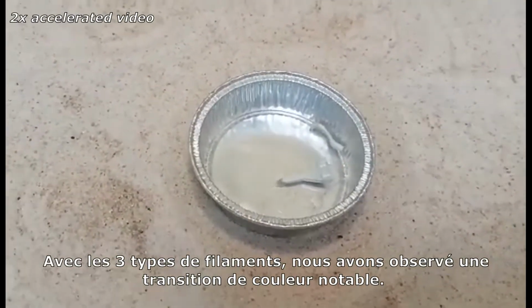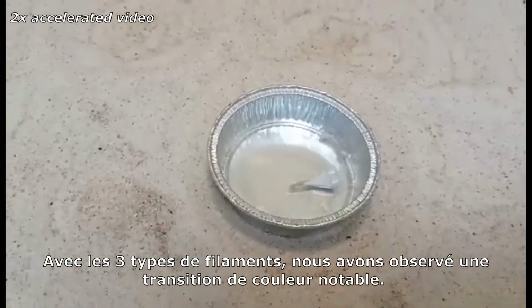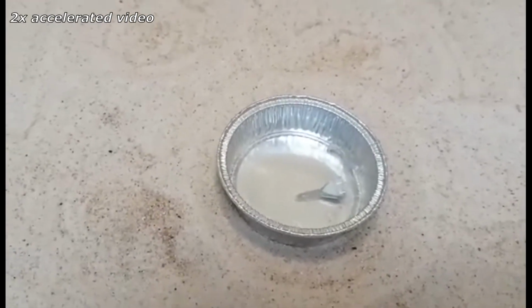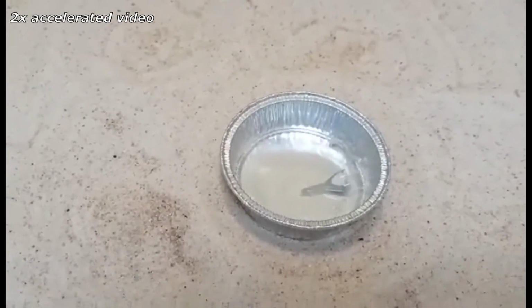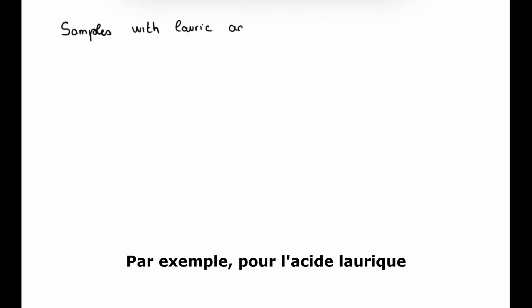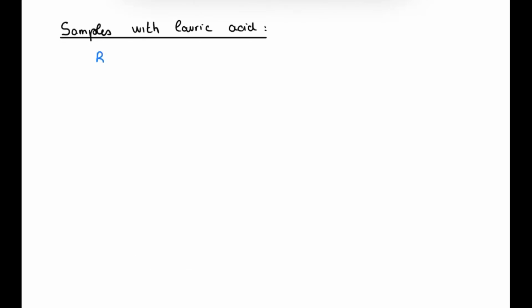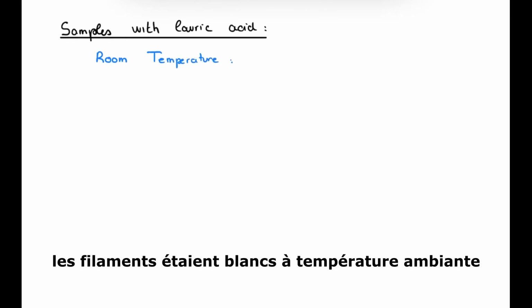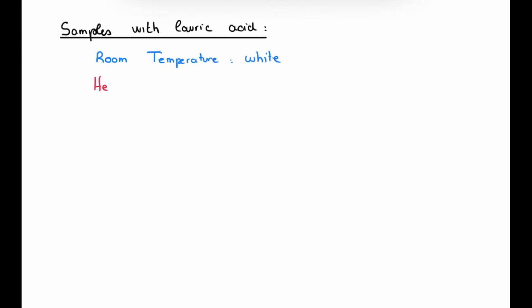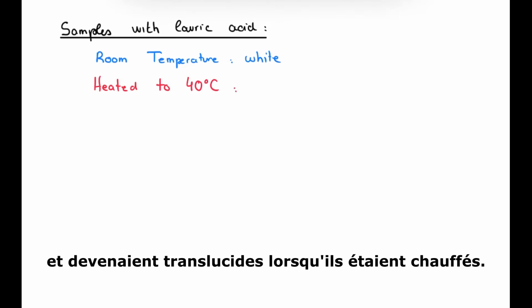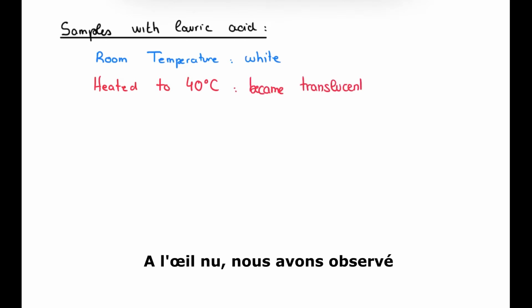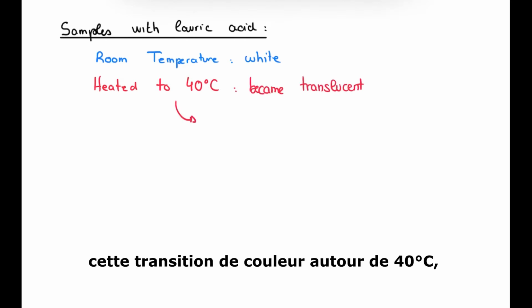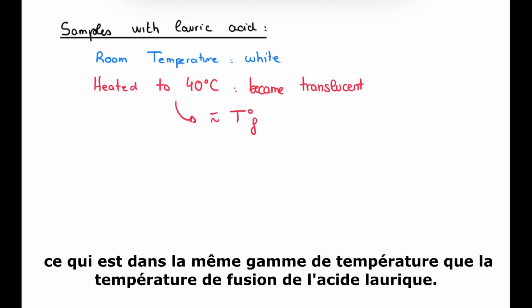With the 3 types of filaments, we observed a noticeable color transition. For samples with lauric acid, the filaments were white at room temperature and became translucent when heated. By naked eye observation, this color transition happened around 40 degrees Celsius, which is in the same range of temperature as the lauric acid melting temperature.